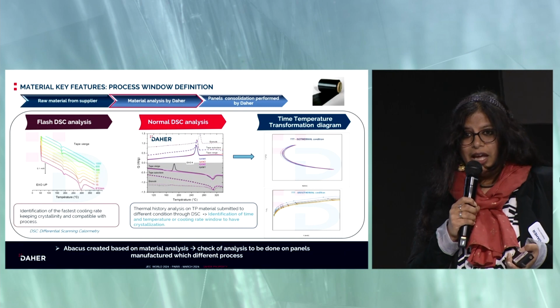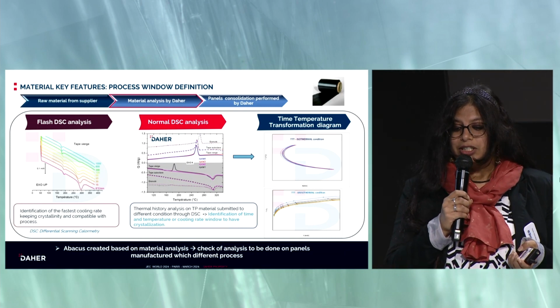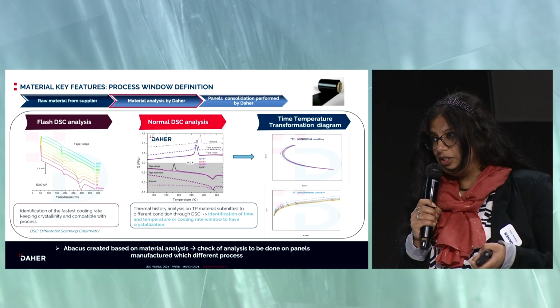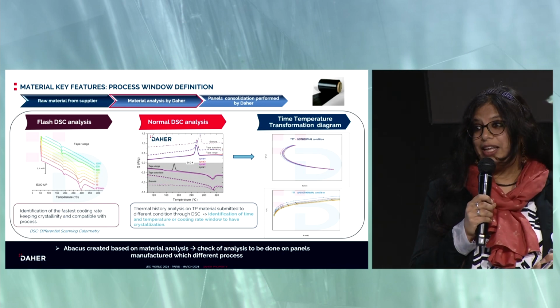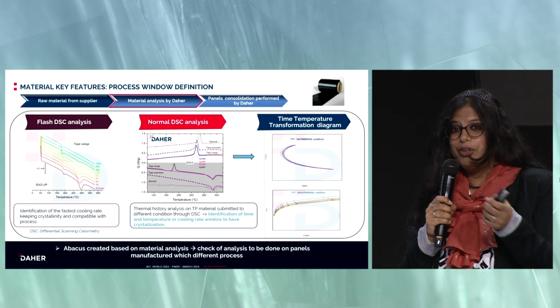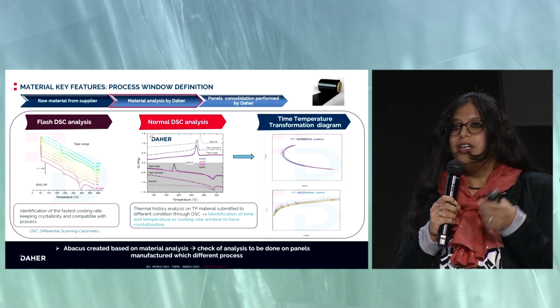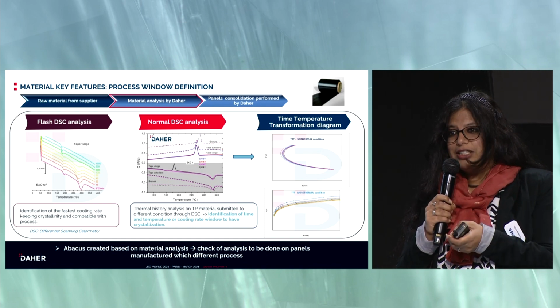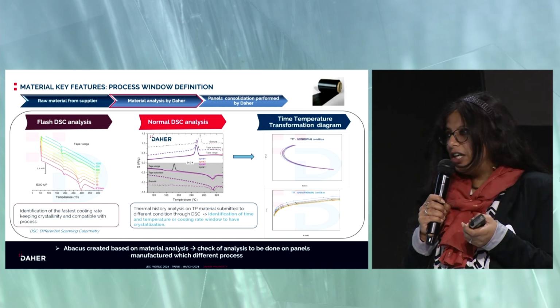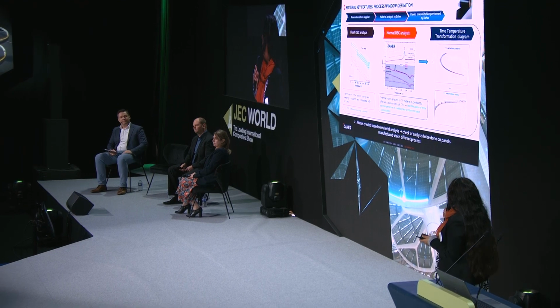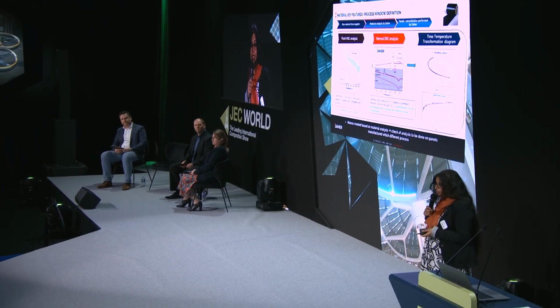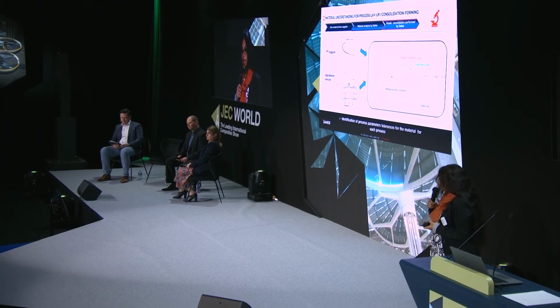We have also done DSC on the part for different times and temperatures, which helps us to have a diagram which is a time temperature transformation diagram. It's commonly used in metals to know what the microstructure is depending on the time, temperature and cooling. So we have taken this aspect and the polymer fundamental analysis into account to have this kind of curve. And with this curve, we know where we have the crystallinity and when the crystallinity does not occur, taking into account an isothermal analysis. With this abacus, we can know how we can then process the material. So it's what I will present here.